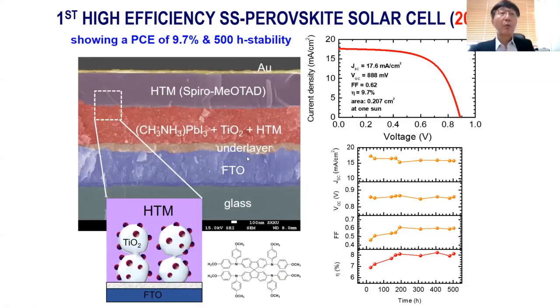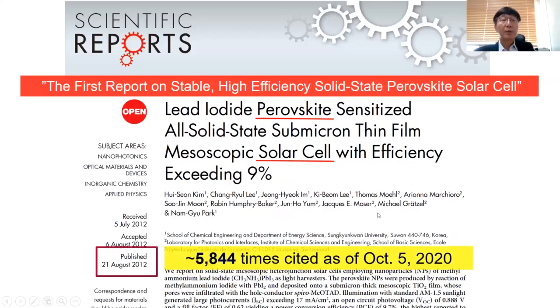Eventually we got 9.7% efficiency, showing 500-hour long-term stability even without encapsulation of the solid-state perovskite solar cell. We first reported the stable, high-efficiency solid-state perovskite solar cell in 2012. And this paper has now been cited approaching 6,000 times as of today.